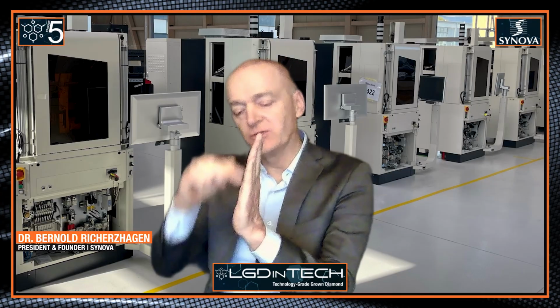And now with this V shape of the laser beam, you are very much limited. That means, for example, if today you want to slice or cut a 1 centimeter diamond stone, you lose a lot of material because you have to ablate, line by line, horizontally, I should say, and you have to remove all the material in this V so that you can go down to the bottom of the thickness of the material. So this makes the dry laser less and less attractive the thicker the material is.